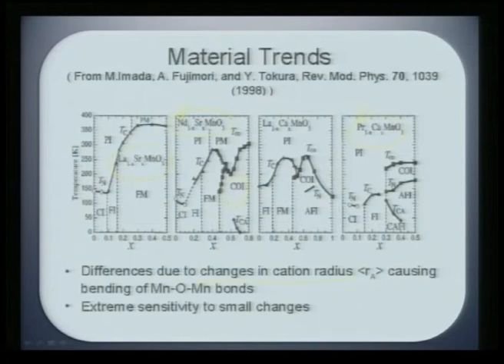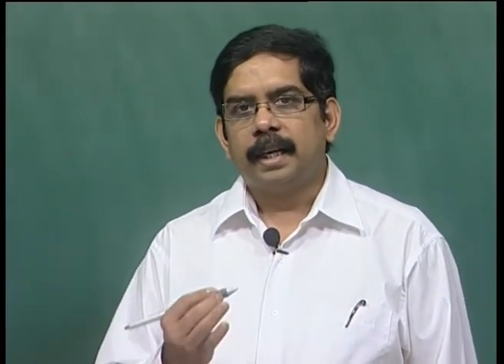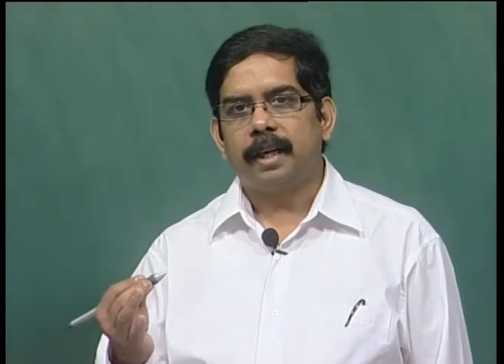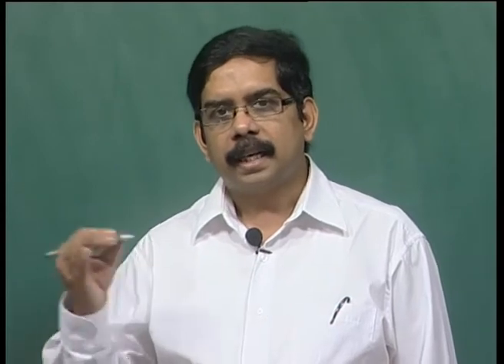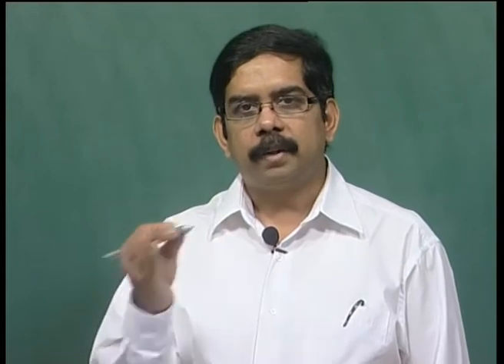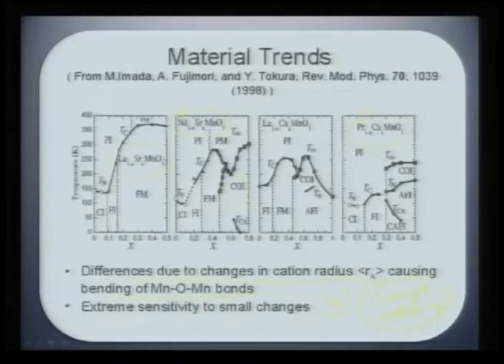So, differences due to changes in cationic radii RA bring about a charge ordering because there is bending of Mn-O-Mn bonds. So, when Mn-O-Mn bonds are distorted or deviate from 174 degrees as I told you earlier, then you actually go into a charge ordered state, which means there is a competing interaction between the itinerant electrons which causes a double exchange mediated ferromagnetism and a super exchange competing magnetic ordering. The super exchange mediated ordering leads necessarily to an antiferromagnetic state. The double exchange mediated ordering leads to a ferromagnetic state, and because you are distorting this Mn-O-Mn bond, you are going into a situation where it is charge ordered.